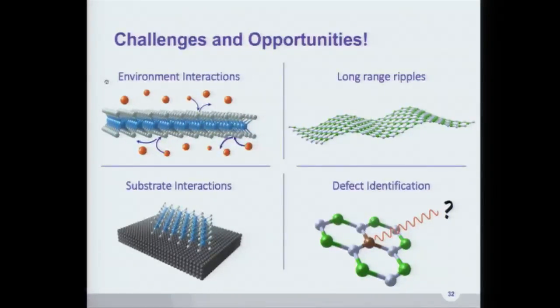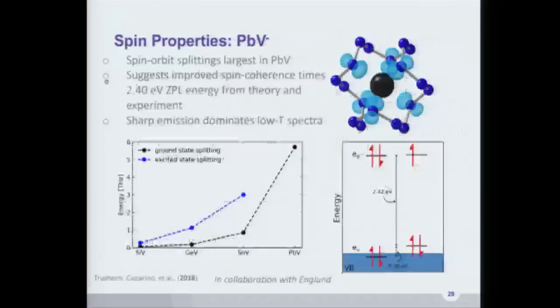So we can address some of the questions in looking at the spin coherence times for these systems. And we're trying to figure out if there's something more general we can say about which distortion and therefore what kind of spin coherence time. Because that would be more of predicting a larger set of trends rather than saying for this system, this is what we expect. But yeah, a rule of thumb would be good enough. Yeah, right. So we're actually working towards that. I'm looking at Chris, who's not making eye contact with me now, to say that yes, we should absolutely do this potentially before the experiment can, so that we actually have a predictive component of the work here.